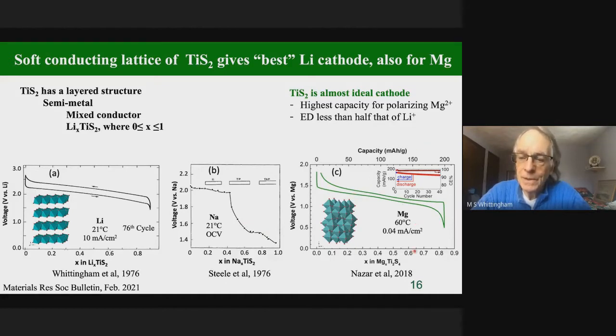And this is work of Linda Nazar at Waterloo University. This is the best data that has been obtained to date on magnesium. You can see a smooth curve, just like the lithium one. The red line shows the capacity with time, again, very good. But to get this to work, she has to go to 60 degrees centigrade and use a much lower current density. So a doubly charged ion has more electrostatic repulsion as it jumps through the lattice, so it moves much slower.